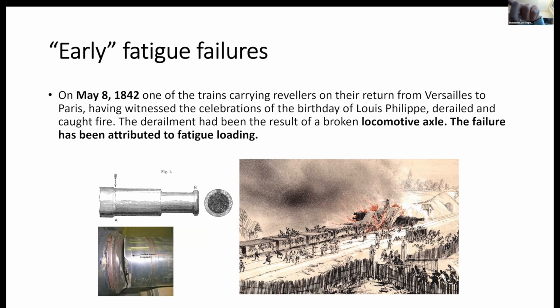So exactly this is what I described before. The axle around has been fatigued. And then when the cross-sectional area was not enough to transfer the loads that it was supposed to transfer, it failed in an abrupt, very sudden way. And that's why we see here this roughness in the surface.